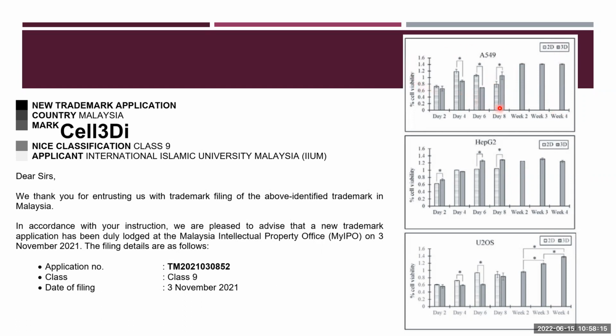And in fact, in another extreme experiment, done only one time, we didn't change the media at all for 5 weeks. We just kept the cells in the media for 5 weeks, and we were able to recover the cells again from the 3D and convert to 2D and continue cell culture as usual. You can keep the cells for 1 month if you don't want to take much care of them. For this one, we actually filed a trademark to make a kit for cell preservation, and generally for 3D cell culture, cell preservation, and cell shipping.